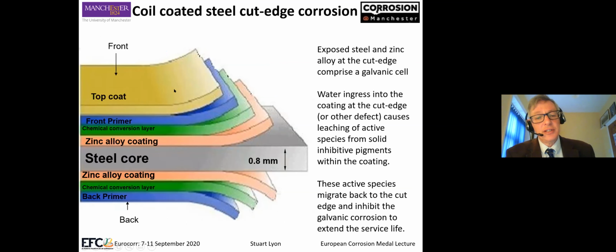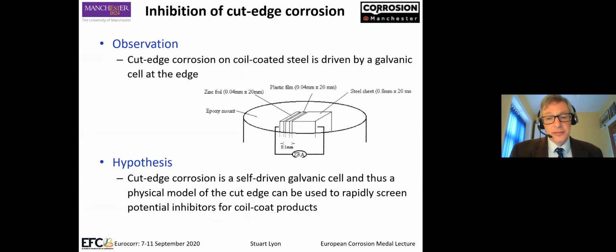Unless the surface is damaged in some way, the cut edge is the only exposed area. So water ingress into this coating at the cut edge, or maybe another defect, causes leaching of these active pigments to that edge. They migrate back to the cut edge and inhibit the galvanic corrosion and extend, therefore, the service life. So on that observation, we said that cut-edge corrosion of coil-coated steel is driven by the galvanic cell.